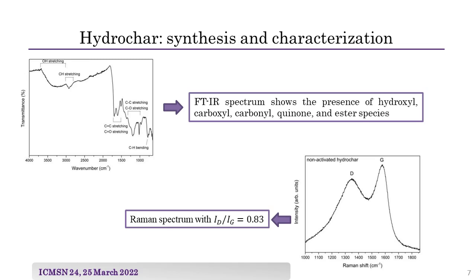In graphitic materials, the intensity ratio of D and G peaks is used to estimate the degree of crystallinity, but in the present case, the intensities of the D and G peaks have to be intended as the peak heights. This is the more reasonable choice because in hydrochars obtained by the carbonization of biomass, the broadening of the D peak is due to contributions coming from distorted clusters with ring orders other than 6. It has been shown that in these materials the D width can be associated to the aromatic breathing mode. Therefore, the information about less distorted rings is contained in the D height rather than its area.